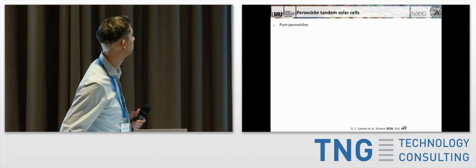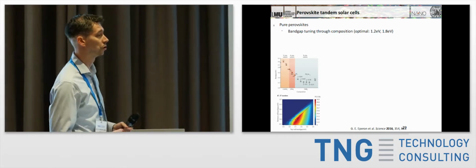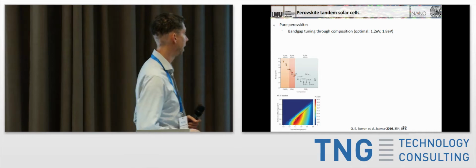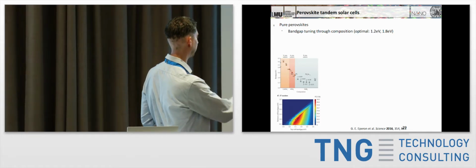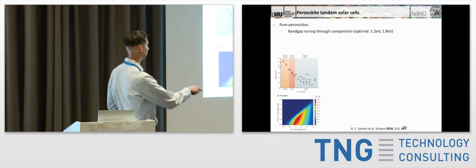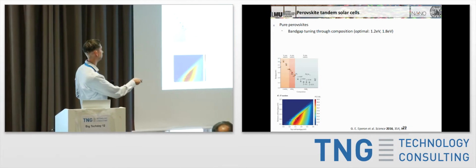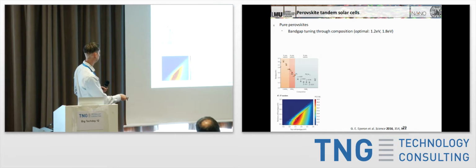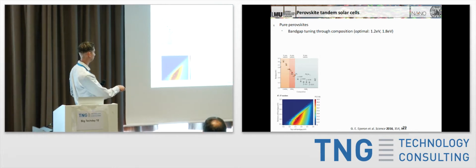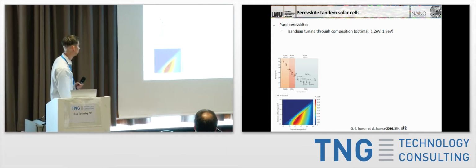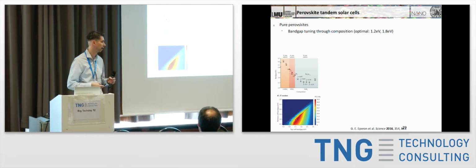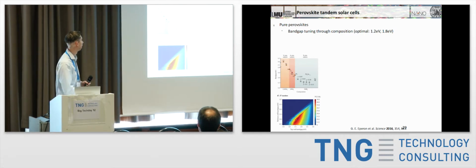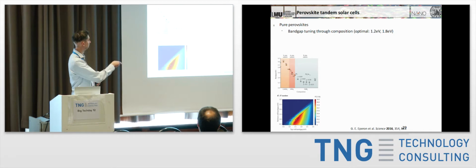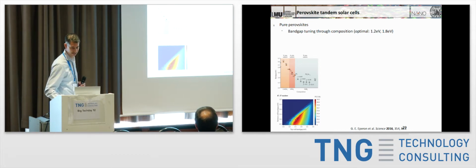It has been, and so using only pure perovskites, because you can tune the band gap of these perovskites, you can actually set them up to the optimal configuration. What's shown here is a theoretical calculation of the bandgap energy of the bottom cell versus the top cell, and in the color-coded is the maximum efficiency that you can achieve. So 46% is the top in red, 0 in dark blue, and you can see there's a relatively large area here that you can tune the band gaps within, so about 1.2 and 1.7 I think is the optimal value. So these are on the border of the NIR region, and you can very nicely replace part of these components in perovskite to basically tune the absorption throughout the entire necessary wavelength range to get this.